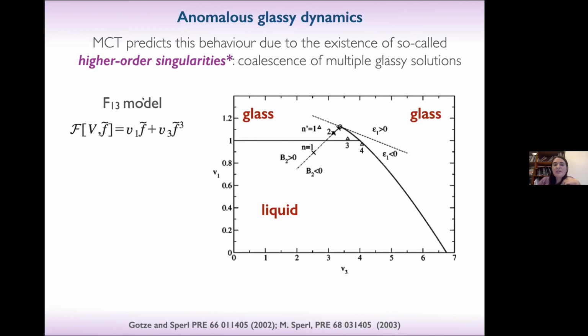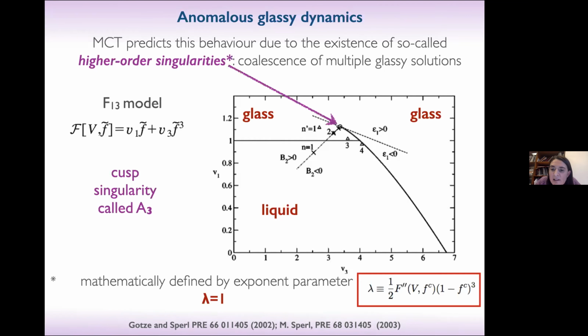model, which has a higher order singularity that in the decoupling language is called the F13 model, in which the functional of the memory kernel, which depends on the vertex, thermodynamic vertex, and the density correlators, is just this simple object. If you solve the dynamics of this, you will see that in your phase diagram that is controlled by this V1 and V3, you have two glassy lines. You go from liquid to glass increasing V1 at fixed V3, but you also go from liquid to glass at fixed V1 increasing V3.